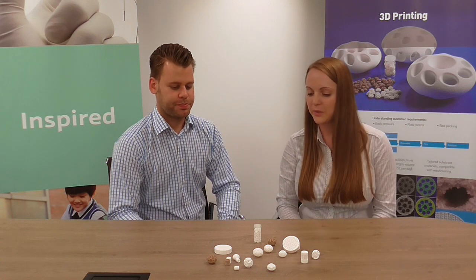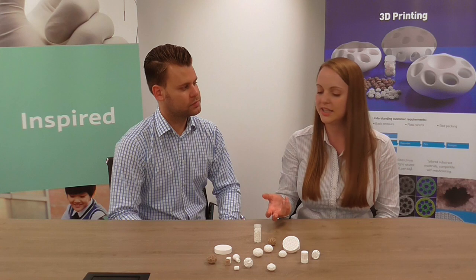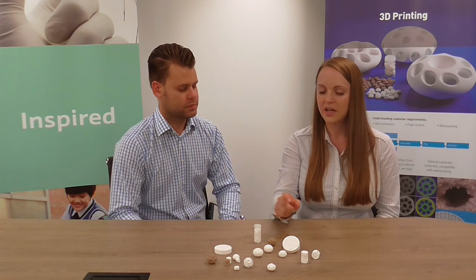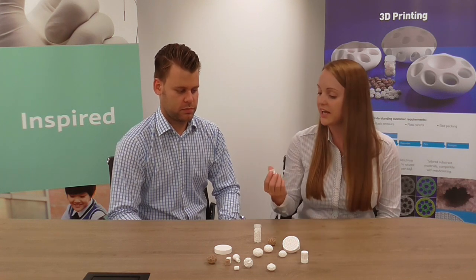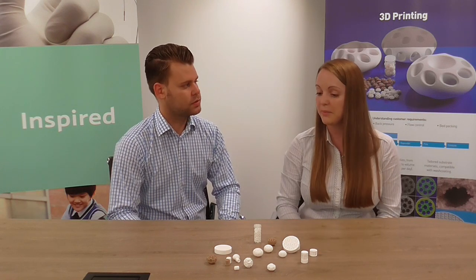What about the speed of production? When you compare this manufacturing method to conventional manufacturing techniques, we are much faster. Going from a design phase to a finished product, including the pre-processing, printing and post-processing, takes about two weeks. If you were to do that with conventional manufacturing and needed to design a new die and press, that would take about six weeks — a saving of about four weeks.